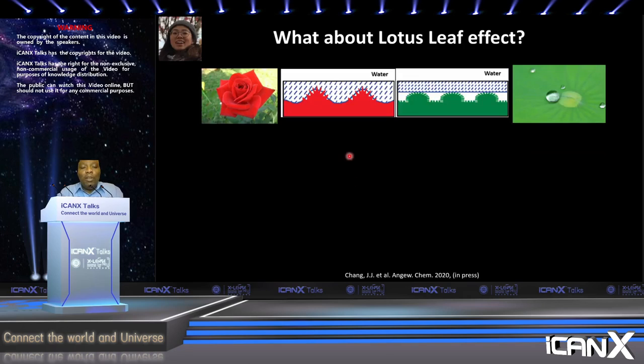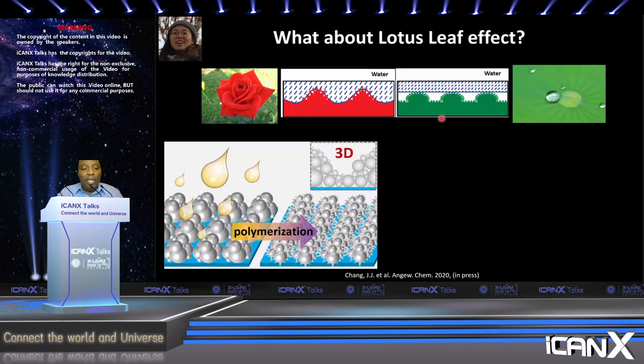But can we go even further? If we can make a rose petal where we see the adhesion, can we actually make something analogous to lotus leaf, where there's zero adhesion, no matter what you try to do? And so here we use some work that we had been developing in the lab to modify the surface of the metal particles that we are using to make the rose flower. And here we're interested in just etching out the oxide and oligomerizing it on the surface to create nucleates and new features on the surface to increase the levels of roughness on the surface of those metallic glasses.